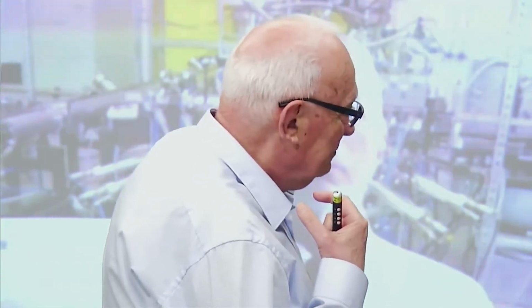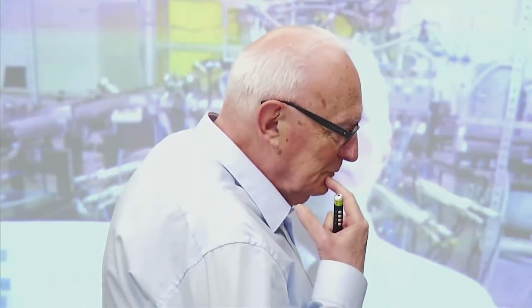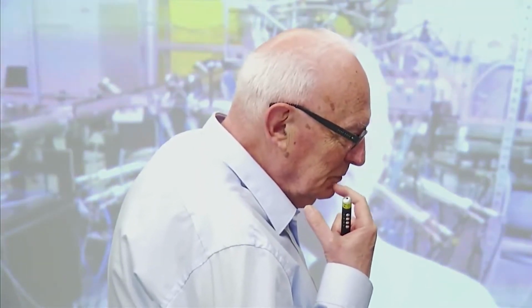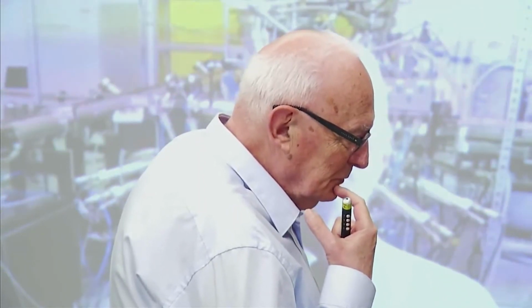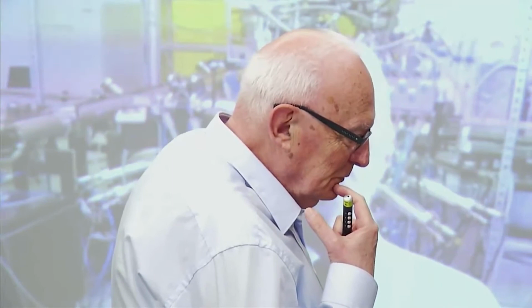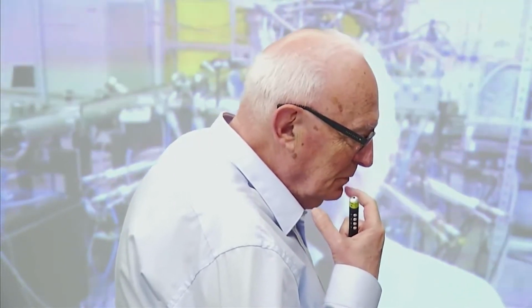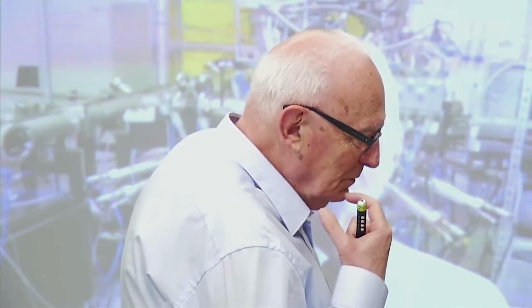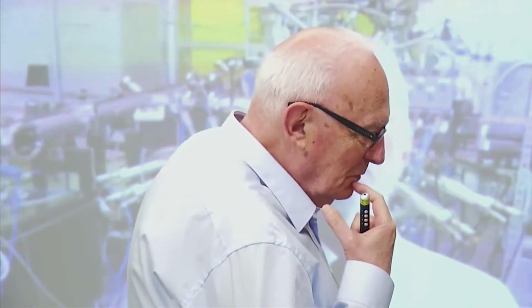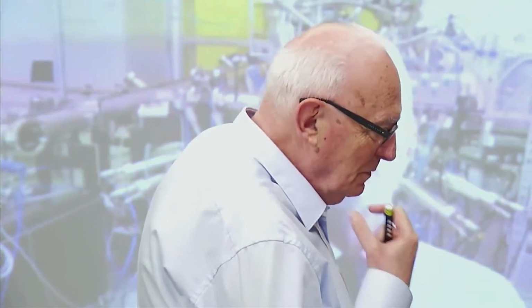So this would be in correspondence to what you have been showing, but for the case of bulk compound. And then also Hashimoto have shown similar measurements for the bismuth copper-based compound. However, he did not see this Fermi level pinning, I would say. They still reported on changes in chemical potential, even in the underdoped samples. So this LSCO compound, even in the bulk form, would correspond to your data. But there is something special in the LSCO. It seems that other bulk compounds do not show this Fermi energy hole doping independence.